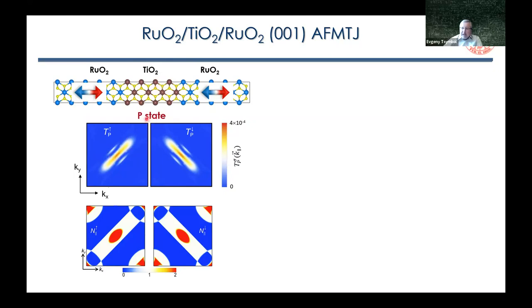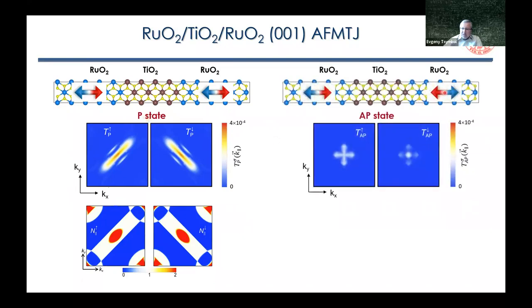So if you now go from parallel state to anti-parallel state, now we switch the Néel vector in the right electrode and compute conductance again. As I've mentioned before, we now have a mismatch in the conduction channels in the left and right electrode, and now transmission is largely located close to the center of the Brillouin zone and substantially reduced, as you can see from this color plot. So if you do summation over all k-parallel to find overall transmission of the tunnel junction and calculate the normalized difference, you'll find a TMR effect, which is of the order of 500%.